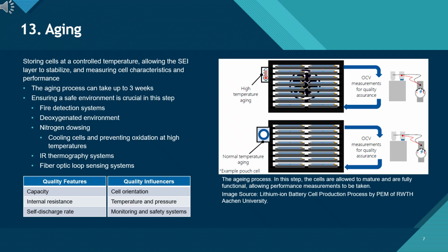Aging rooms are equipped with fire detection systems, nitrogen or deoxygenated environments, and cooling or suppression systems that prevent thermal runaway. IR cameras and fiber optic sensors monitor temperature trends across the racks to ensure no cell deviates from expected behavior. By the end of aging, each cell is fully stabilized, and its key performance characteristics, capacity, internal resistance, and self-discharge rate are verified before moving to final inspection and shipment.